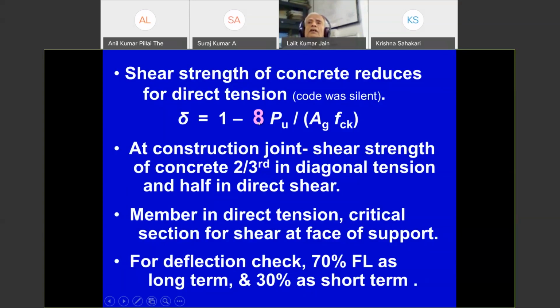In the last many years, this constant was being debated. The values were cut off between 5 onwards. Today we have taken a value 8. If you see the Australian code or New Zealand code, they have taken a value 12 here. So maybe in future, because cracking is more important in water retaining structures, this constant will be revised a little upward. But now it is introduced that the shear strength of the concrete goes down when there is direct tension. So whenever there is direct tension, in most cases, in slabs and panel walls, etc., there is something like a 10 to 20%, 30% reduction in shear strength. That has to be accounted in design.